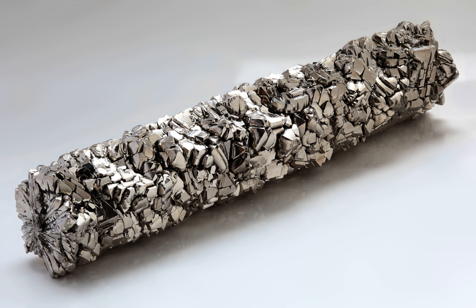Titanium is capable of withstanding attack by dilute sulfuric and hydrochloric acids, chloride solutions, and most organic acids. However, titanium is corroded by concentrated acids. As indicated by its negative redox potential, titanium is thermodynamically a very reactive metal that burns in normal atmosphere at lower temperatures than the melting point. Melting is possible only in an inert atmosphere or in a vacuum.